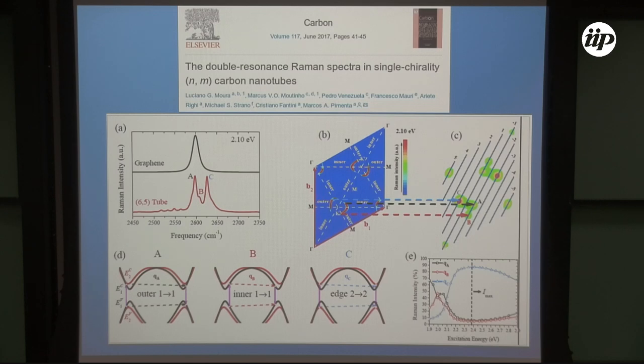So you don't see the symmetry of the 2D peak that you see in monolayer graphene because now you have three sub-peaks. Okay? So we can say exactly, from the electronic structure of the carbon nanotube, what are the electronic processes that are taking part in each of these three sub-peaks here. And this could be used, for instance, to say in an easier way what is the chirality of a sample with enriched carbon nanotubes.